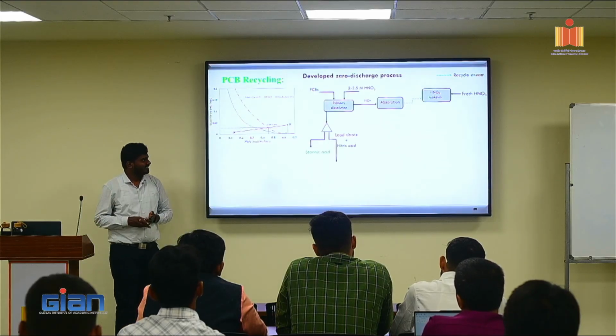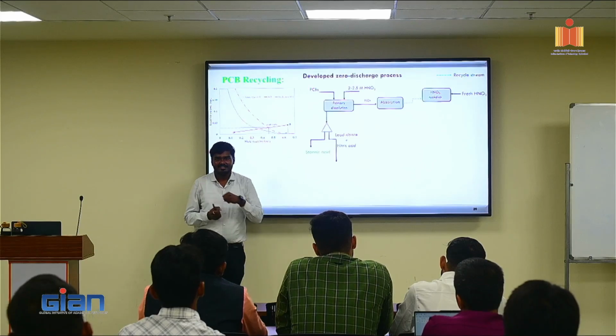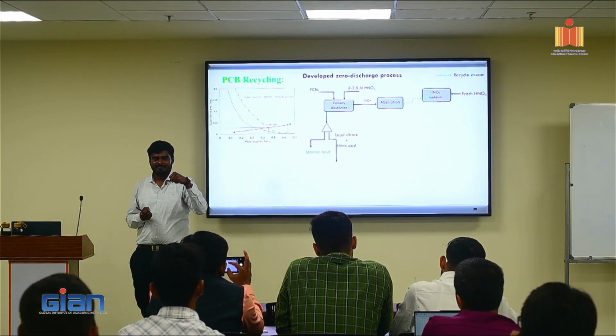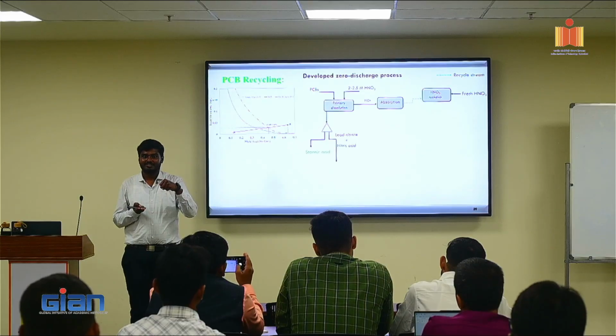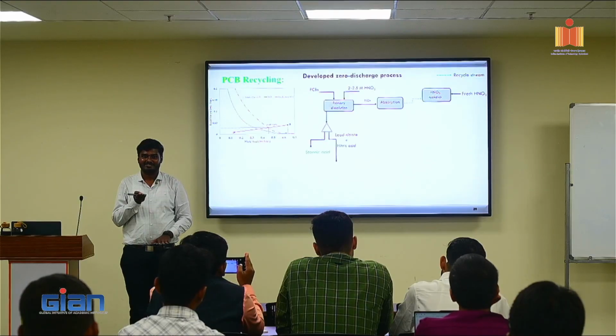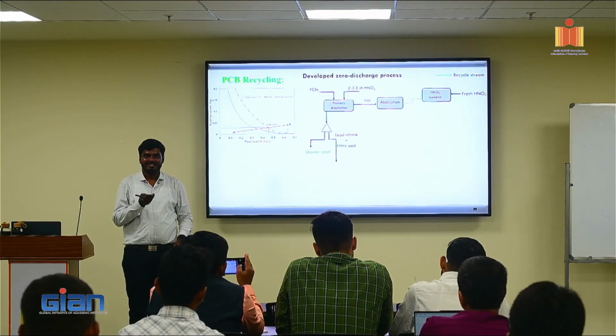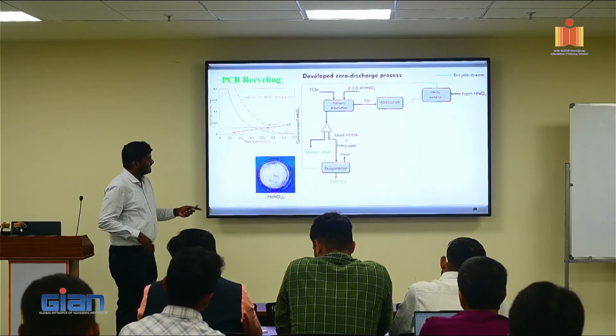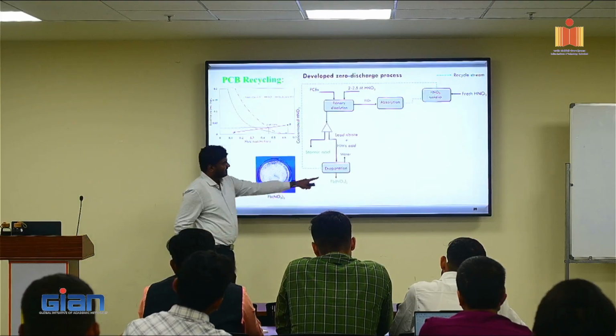Now I have a mixture, right? This lead nitrate, nitric acid. If I can separate water from it, then the nitric acid concentration will increase. When nitric acid concentration increases, the solubility of lead nitrate will decrease and typically it will crystallize. So that's what we did. We just did evaporation and we separated water.